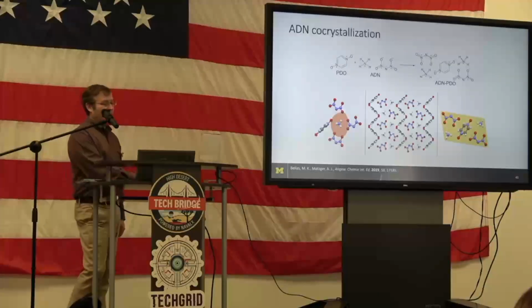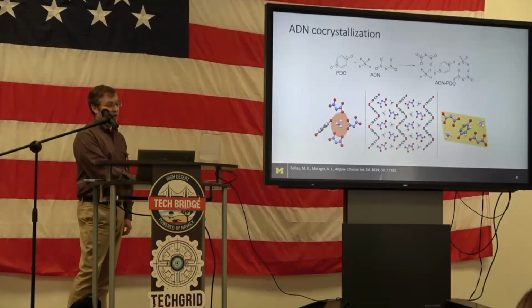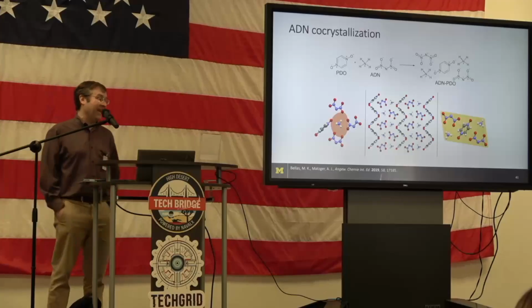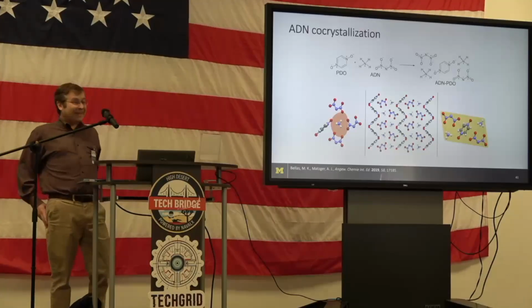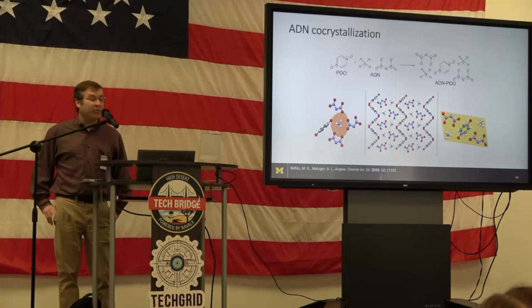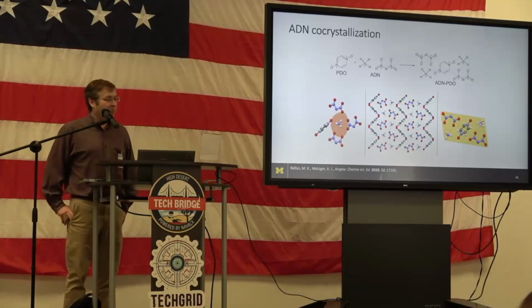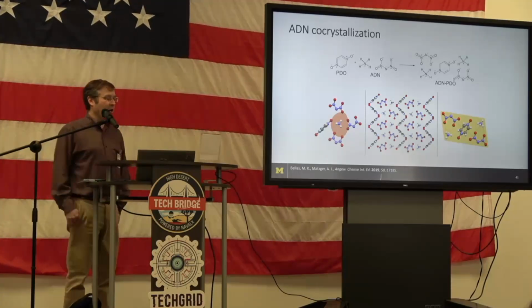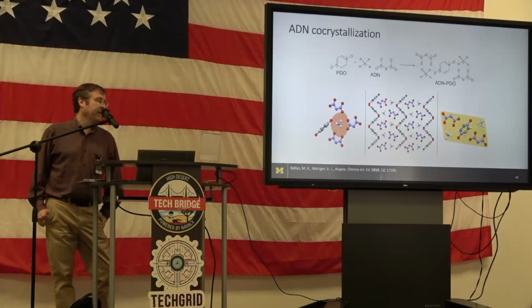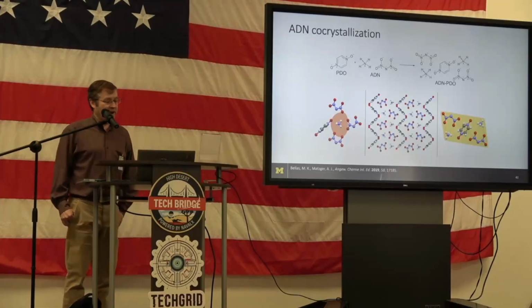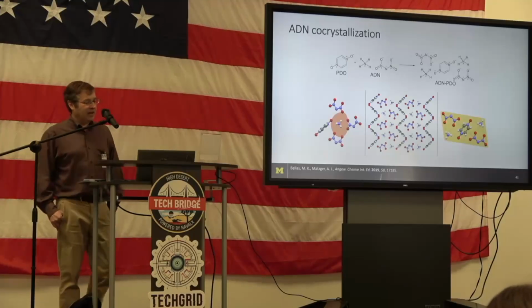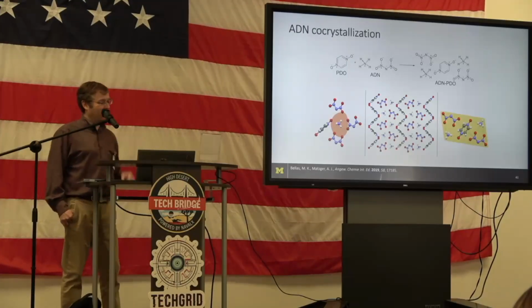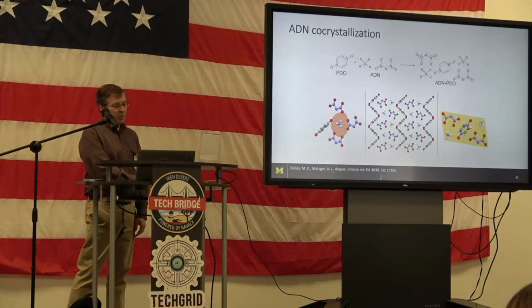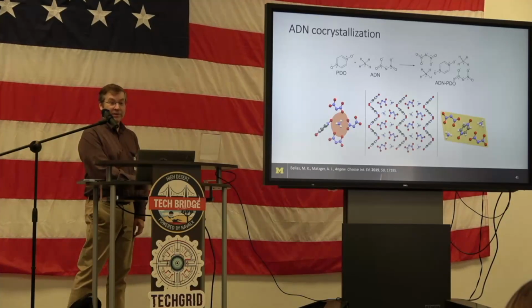And so what worked out very well was this pyrazine bis N oxide. So we predicted that this would be a good hydrogen bond acceptor from the ammonium that would allow us to co-crystallize ammonium dinitramide. And indeed, this worked out really well, and it got us actually thinking in all kinds of new ways, because we were finding that basically this looks very much like the salt here, and then it looks like your coformers in between.